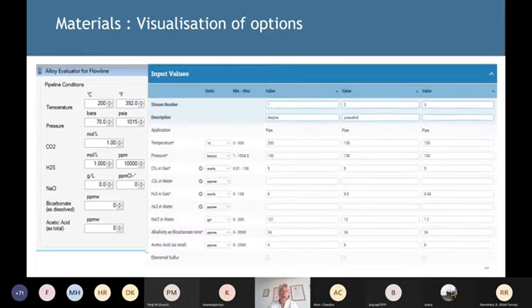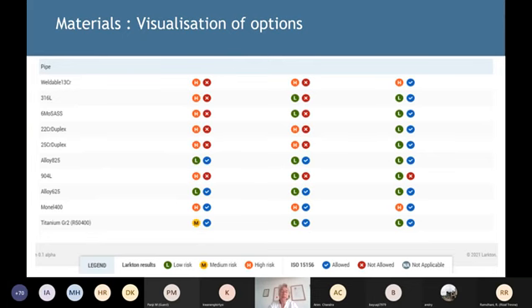In Larkton CM, you have your input values to put in, and you can have multiple streams to analyze at the same time. And when you analyze these, you'll get a list of materials and then two indicators. One is whether the material is allowed or not allowed in the ISO standard, and on the other hand, whether it is a low, medium or high risk. So let me just remind you that in both ECE and Larkton CM, the approach is that the ISO standard is there only to give you guidance about cracking in sour service, sulfide stress corrosion cracking only, whereas the risk evaluation is saying that these materials might suffer general corrosion, pitting corrosion, chloride stress corrosion cracking internally and so forth.